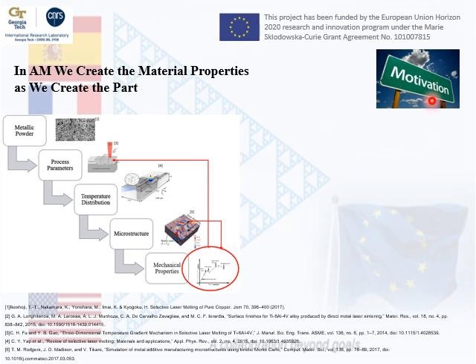So the material is subject then to very high cooling rates. In addition, there is a very directional heat flow gradient, and for that reason, the microstructures show characteristics that are not usual in conventionally processed materials. So for example, we usually observe columnar grains, but depending also on the processing parameters, there are different microstructures that we may expect.